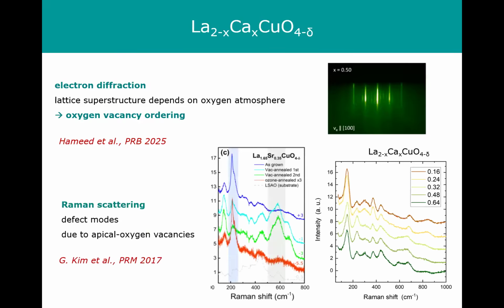Okay. And we can also see direct evidence of oxygen vacancies by Raman scattering. This is work done again by Gidok Kim some time ago. On the left-hand side, that is published work on lanthanum strontium copper oxide, where you see in the middle plots, graphs here, these pronounced peaks that are characteristic of oxygen defects. And by changing the polarization geometry, you can actually find evidence that this is due to apical oxygen vacancies.